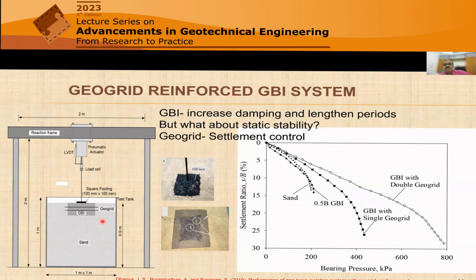If you do that, you see this is the pure sand. Obviously, if you don't have a geogrid, it will settle much more. But as you increase the layers of geogrid, single layer geogrid and double layer geogrid, you will get adequate bearing capacity with the reduction in the settlement.